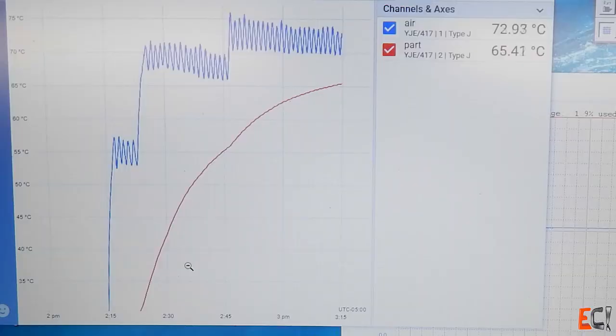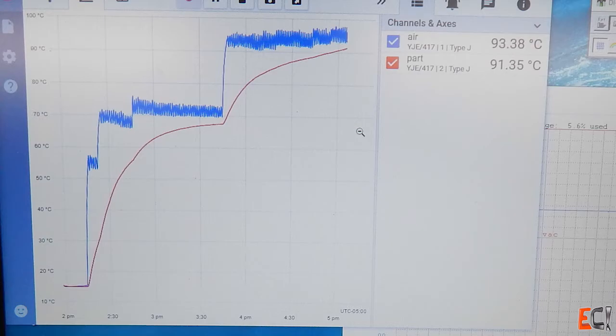That's the part going up to its first dwell sort of dwell around 65C and then ramped up further. I should have ramped this hotter faster and we'll see in a minute why but that's the beginning of the cook. The log went nice.